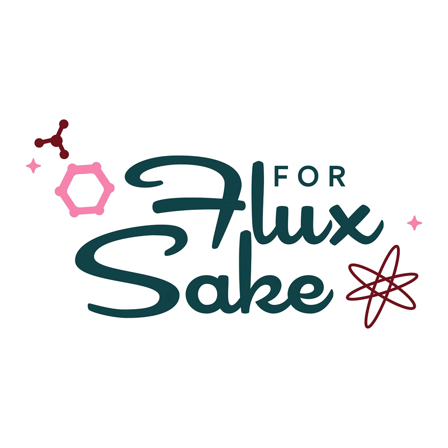It may be cone 5 3/4. It could be even smaller fractions than that. And that's all glazes, cone 10 glazes, cone 6 glazes. So people started throwing 10% Gerstley borate into their glaze and it would probably work. And that just became the way most people were converting to cone 6. But it also led to really lazy, sloppy chemistry. When you look at all these old recipes, they're kind of a disaster.